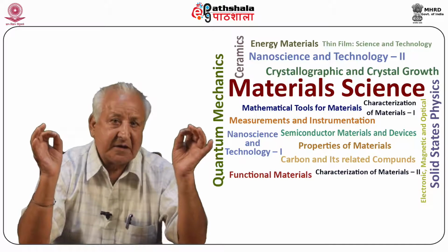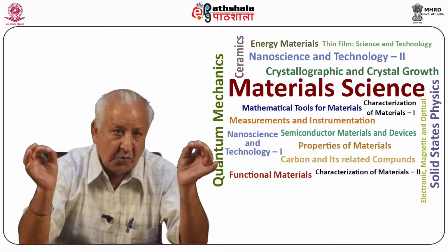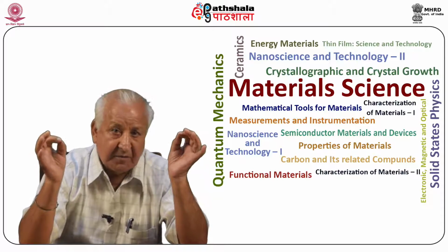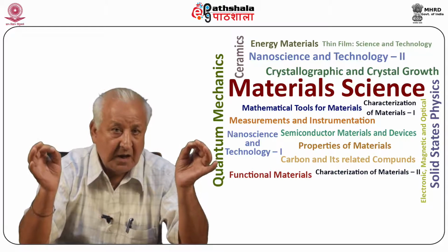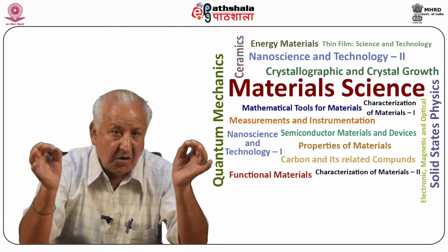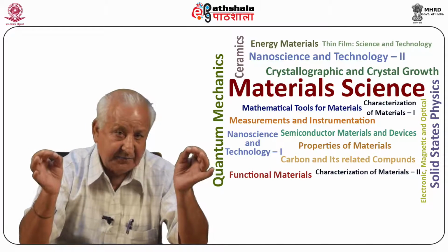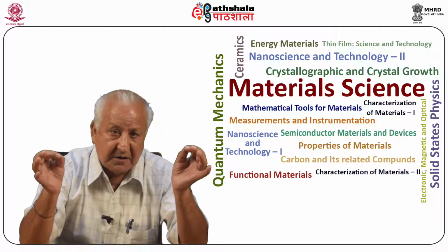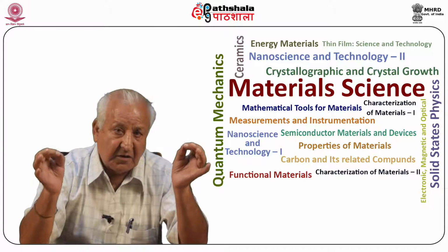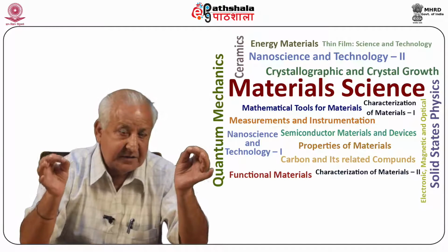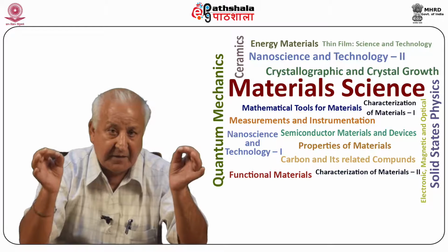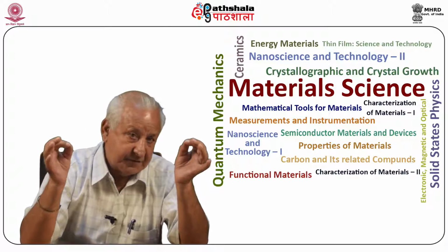Elastic deformation is caused by strains which obey Hooke's law. According to Hooke's law, atomic displacements are proportional to the applied force. When the elastic limit of a solid is exceeded, permanent or plastic deformation sets in. In many crystals, it occurs by slip. Theoretical estimates of the elastic limit of perfect crystals yield values 10 raised to the power 3 or 10 raised to the power 4 higher than the lowest observed values.